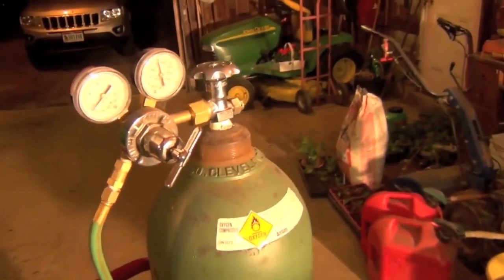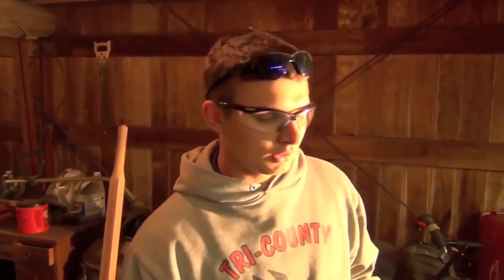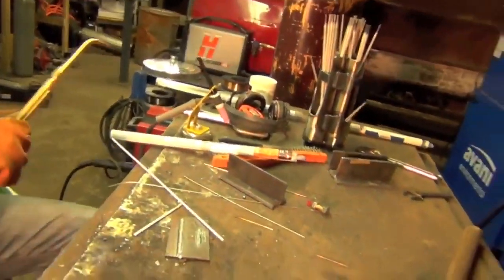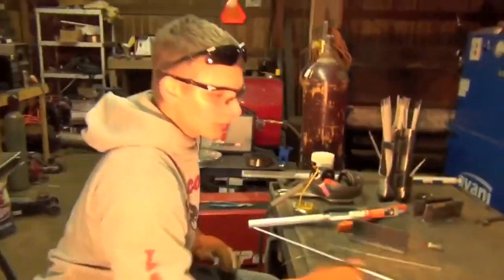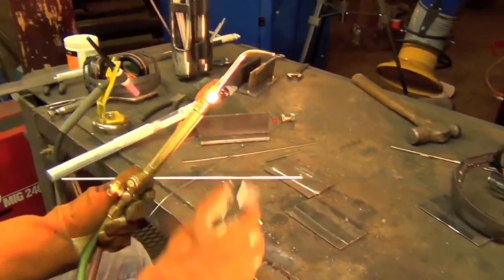You don't have that cutting jet of oxygen coming down, so that's what really uses the oxygen when you're using the torch. We'll come over here, get situated, find our striker. You get spoiled after TIG welding where you just pull the trigger or push the pedal to get heat going. There's a little bit more of an art to setting the torch than you might think because you can get a lot of different heats out of the same torch just based on your gas flow. It's easier to turn the heat up than to turn it down without putting your flame out. When your smoke starts to go like that, give it a little oxygen, put it to a neutral flame. That's probably going to be pretty good. A low heat seems to work better for these. It's a little more controllable, you don't have the foot pedal like TIG.